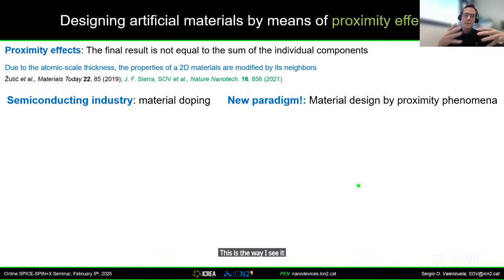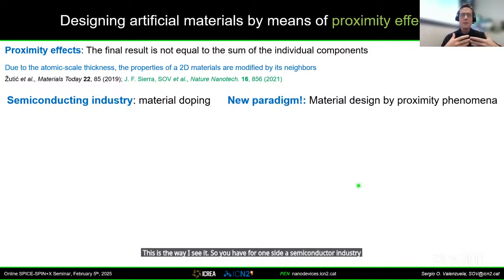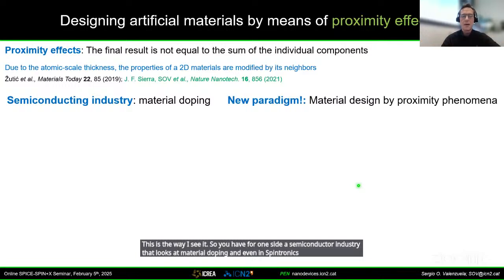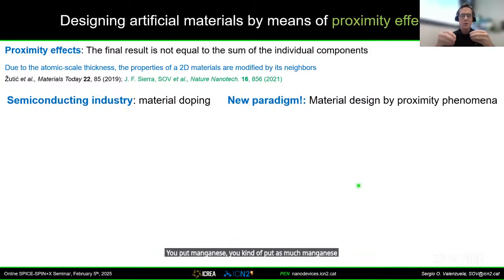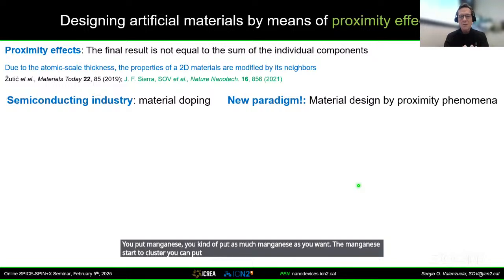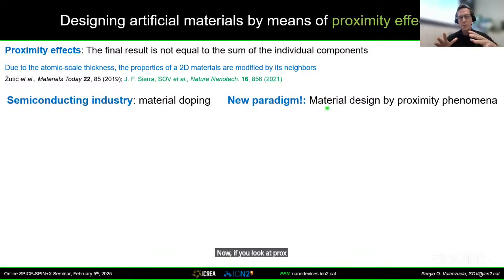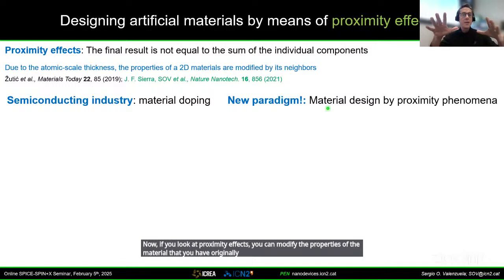So you have, from one side, the semiconductor industry that looks at material doping, and even in Spintronics in the past, we tried to make, and some people succeeded in making, gallium arsenide magnetic by putting manganese, but that led to a lot of problems. You put manganese, but you can't put as much manganese as you want. The manganese starts to cluster, so you can put a few percent. You also modify the transport properties of gallium arsenide, which can have very high mobility without manganese, and then it drops very fast. Now, if you look at proximity effects, you can modify the properties of the material that you have originally with an insulator, and then introduce different properties into it without modifying the nice transport properties that you have originally.